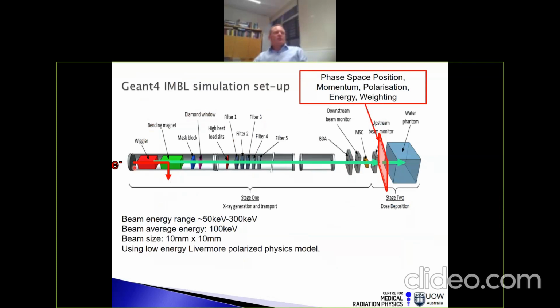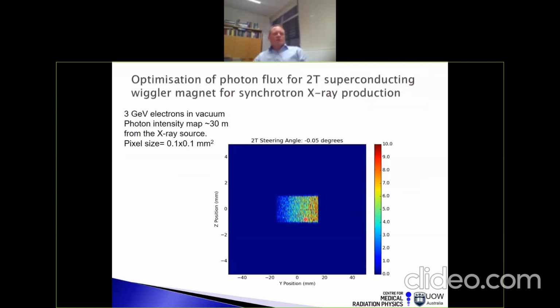We've simulated the whole beamline, including the production of the synchrotron X-rays itself. This is the superconducting wiggler that I spoke about before. The electrons come through here, they wiggle in the wiggler in the magnetic field, and then they go through the bending magnet around the synchrotron, and of course, the photons come straight through. We've modelled all of this, and this is just an example. Here we're modelling the steering angle. Depending on the incident angle of the electron into the wiggler, that determines where the maximum flux is for the corresponding photons that are coming out. So that all needs to be optimised. We're simulating our whole experiment with Monte Carlo radiation transport. Extremely important, and that's exactly what we do experimentally too, when we go and do experiments at the synchrotron.